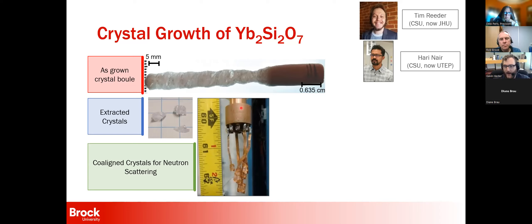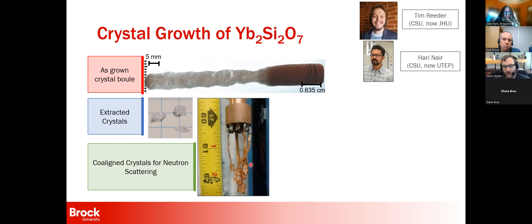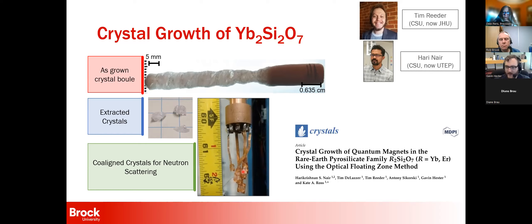That's actually what we ended up doing for our neutron scattering experiment. At the top is a copper mount that attaches to a refrigerator in a neutron scattering instrument, with long copper legs going up to little copper plates where we strapped and glued crystals. Since ytterbium silicate doesn't grow as one large crystal, we need more mass to get a measurable neutron scattering signal, so we use multiple crystals all aligned in the same direction to act as one larger crystal — roughly a gram of crystal was co-aligned in this experiment. We strapped them down with copper thread and used a fluorinated glue to secure them.